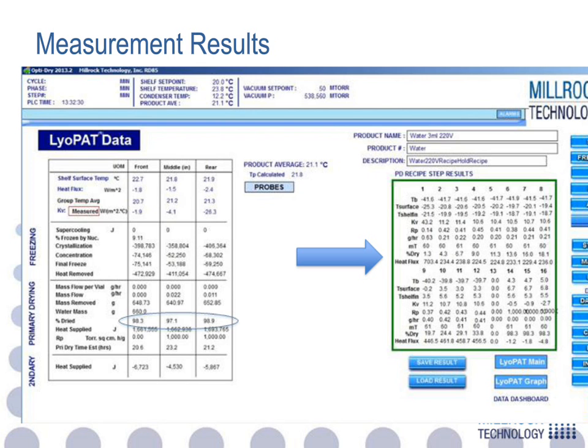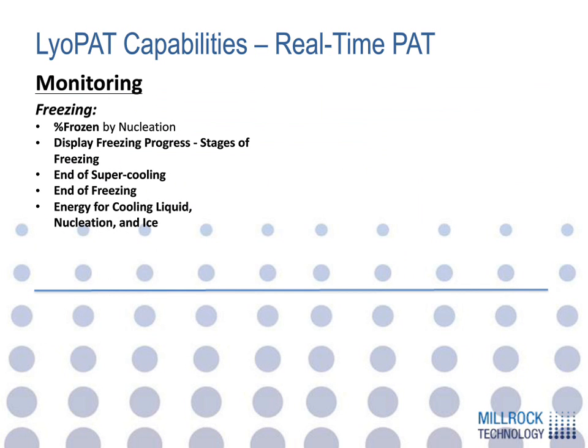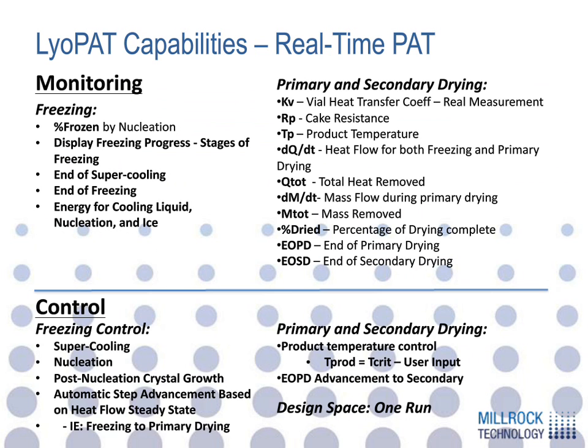So if we take a look at some of the information that we do get out of the system, here are some of the things that we can actually see and monitor. Because of the heat flow, we can actually see the end of the supercooling and the freezing. We can watch the energy for nucleation and crystal growth and things like that. During primary drying, we have KV, cake resistance, product temperature, heat flow, mass flow, total heat removed, mass flow per vial, percent dried, end of primary drying, and secondary drying if you really wanted to. And this is all available through the software. So the long answer to the question is yes.